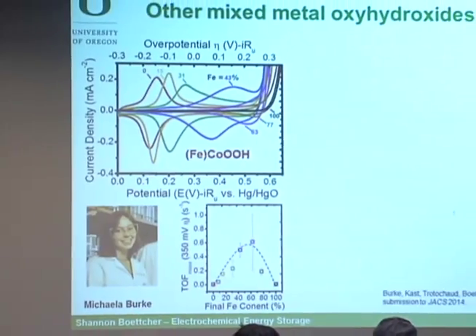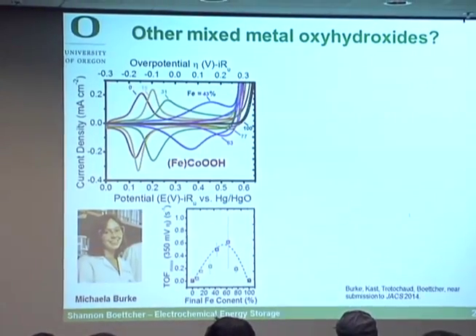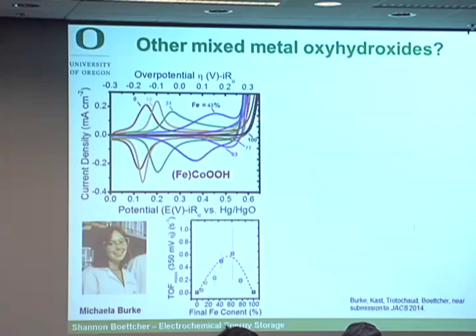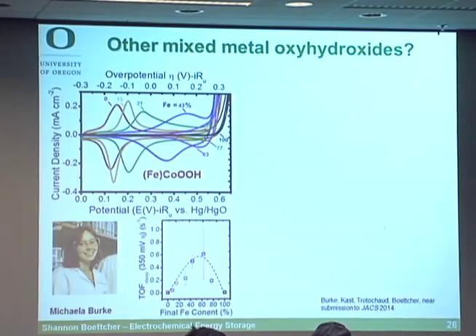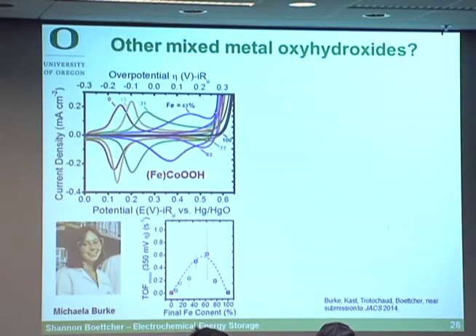Okay, so we're doing other experiments. We're looking at other mixed systems to try to understand the various activity trends we see. So here's some data for an iron cobalt system. And you see very similar trends. As you incorporate iron into cobalt oxyhydroxide, you see the oxidation wave of the cobalt now shift to higher potentials. You see the activity increase. The change in activity going from ultra-pure cobalt to iron-doped cobalt is not nearly as large as in the nickel systems, but it is significant.